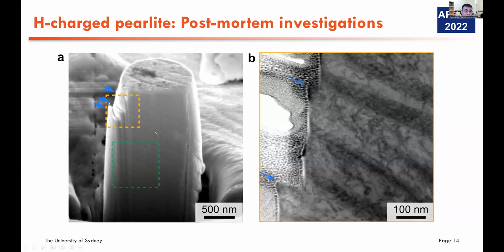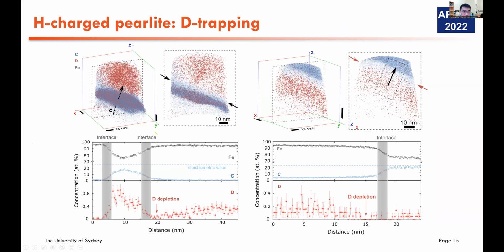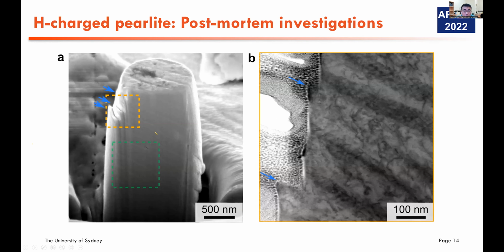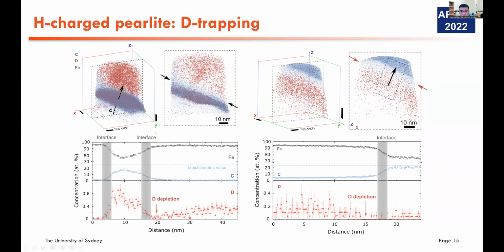So this is hydrogen atom probe tomography with the cryo-transfer technique, with hydrogen charging and cryotransfer. You see the black one here represents carbon, the red ones represent deuterium, and this is a cementite phase. And if we plot this as a concentration, you will find that actually deuterium is depleted at the interface, instead of segregating to it as people usually believe. And we also believe that this depletion is the reason for that slip offset from the interface. And to repeat the experiment, we have another dataset to show the deuterium depletion at the interface.